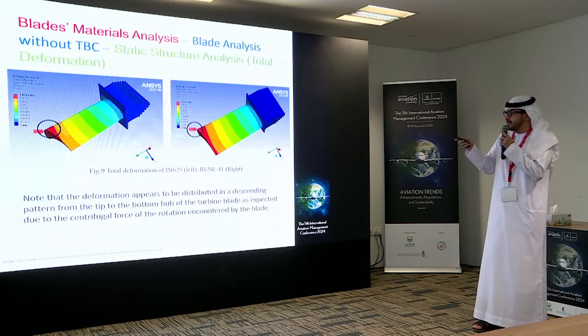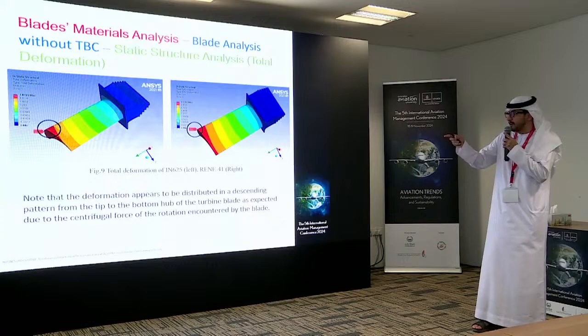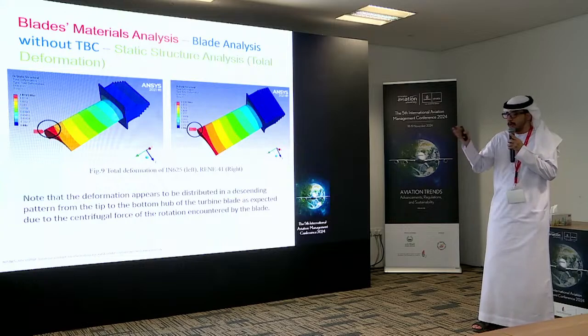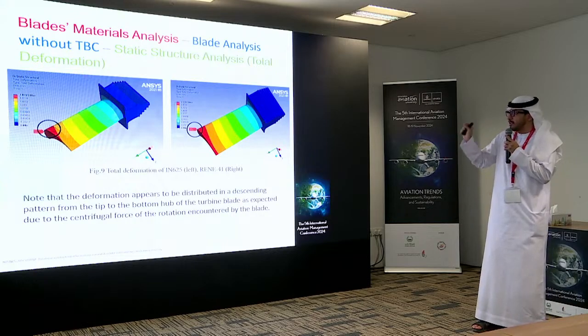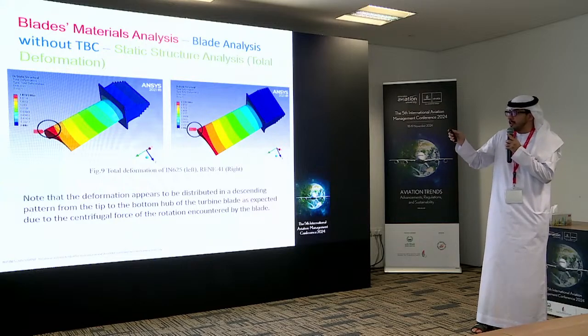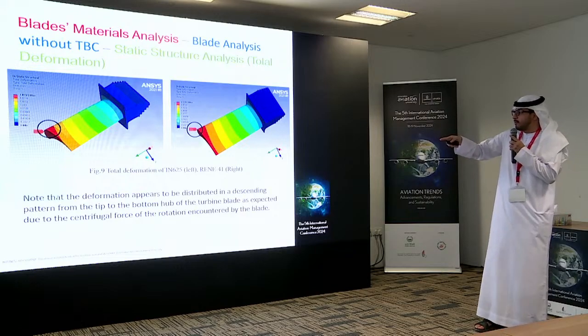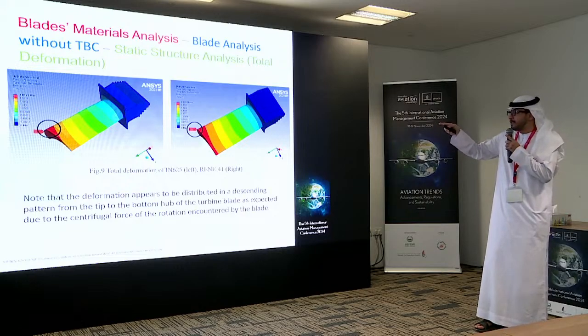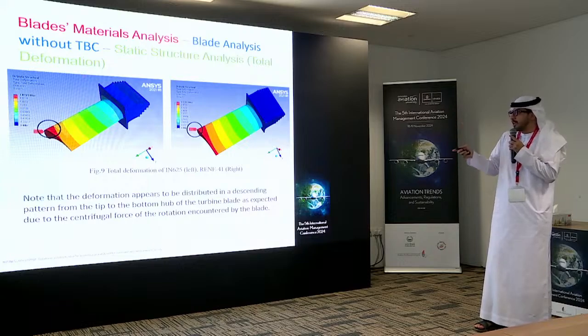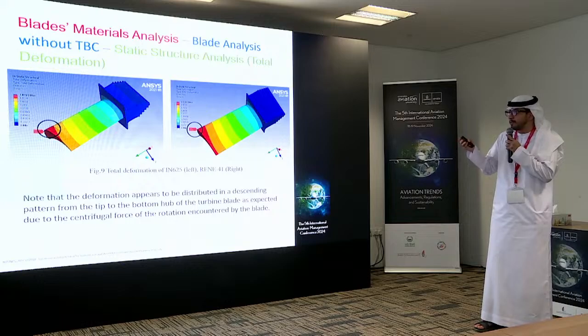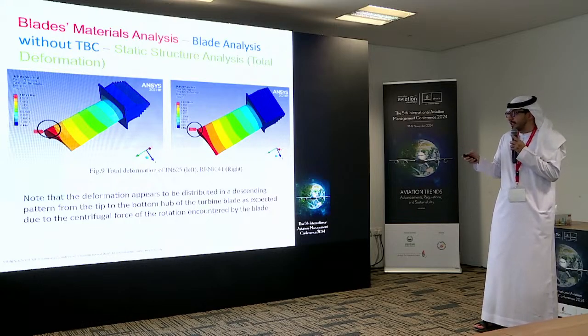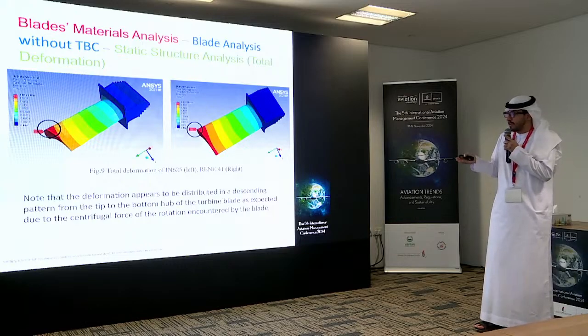First of all, for the static structure analysis, here we have on the left side the total deformation for the Incoloy 625. As you can see, on the right-hand side we also have the RENE41. It's another superalloy material. After we applied the boundary conditions, we notice that on the tip of the blade itself, there's a deformation of 1.8 millimeters. However, for RENE41, you will notice 2.2, which is higher than the Incoloy 625. Here it shows you that the Incoloy 625 has superior properties in terms of the total deformation, and it can withstand higher than the RENE41.